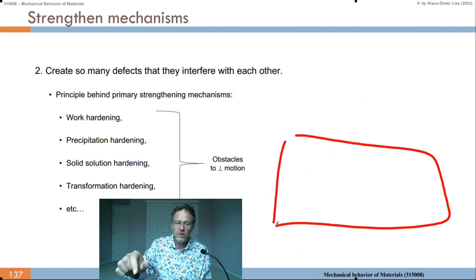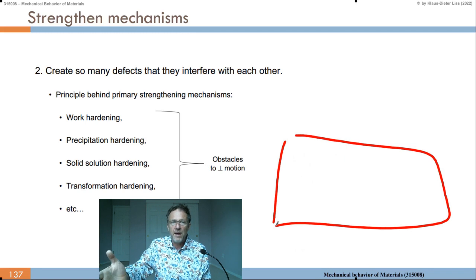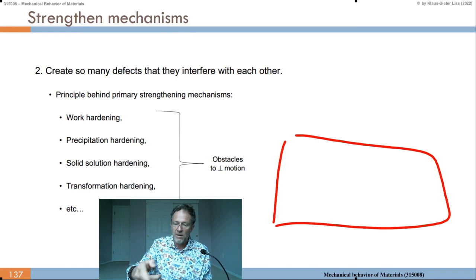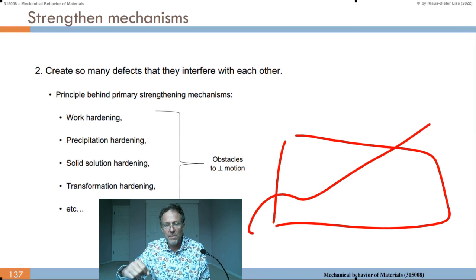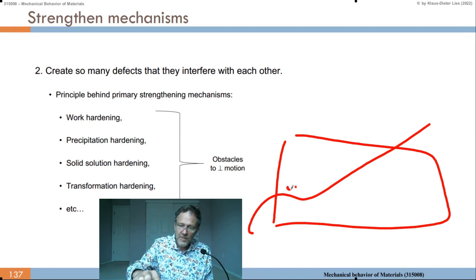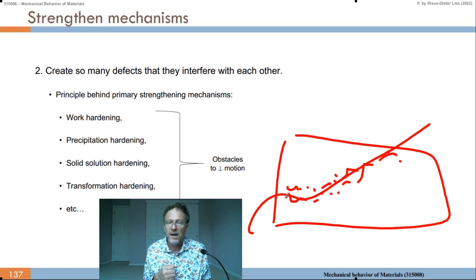Then we have solid solution hardening. We know we can have a solid solution, dissolve some impurities in the alloy. So if we have iron here, we can put carbon in, and then we have a dislocation. We know the carbon goes on interstitials. So the carbon will precipitate into the strain field of the dislocation. So it will accumulate around the dislocation, because if you expand the lattice, where you have a tensile strain, then you have more space in the interstitials, and that's where the carbon would go.